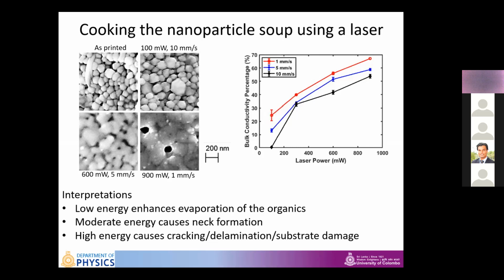That means we simply increase the evaporation of the organics, but nothing much. That is at lower laser energies. At relatively moderate laser energies, for example, 600 milliwatt at 5 millimeters per second, that is the second row first image, you can see a clear difference between that and the microstructure of an as-printed trace. You can see that the particle sizes are bigger now. That is called grain growth. The size is bigger, and also there's an improved neck forming, the welding of particles together. So we increase the neck formation and welding just at moderate energies.